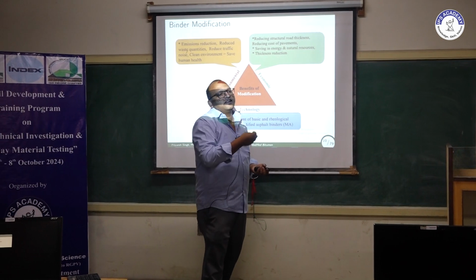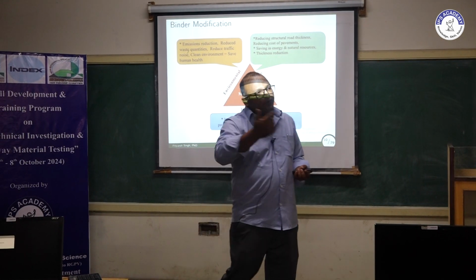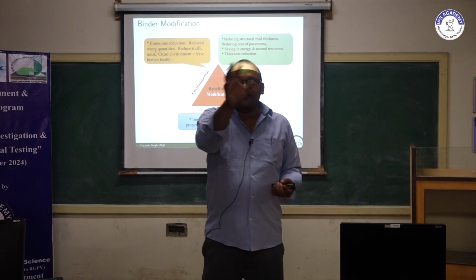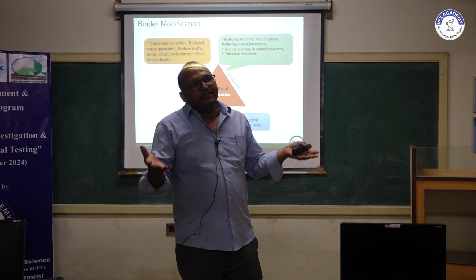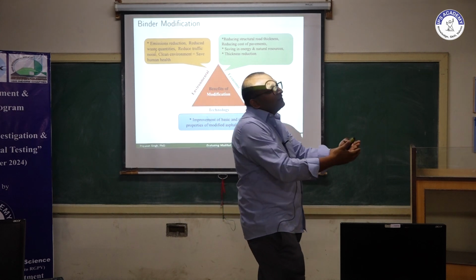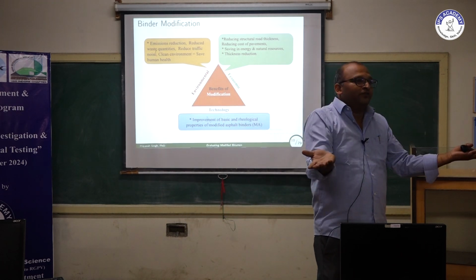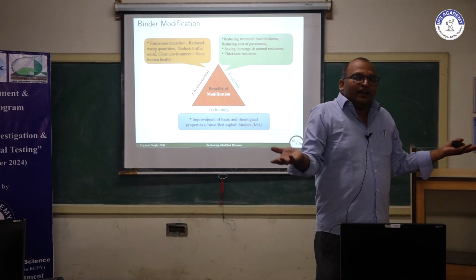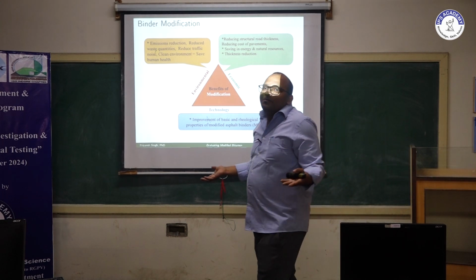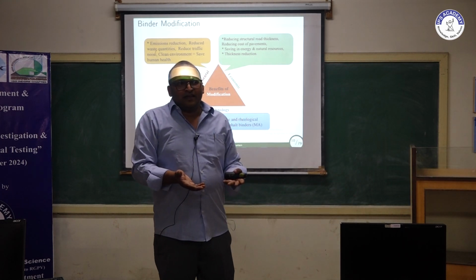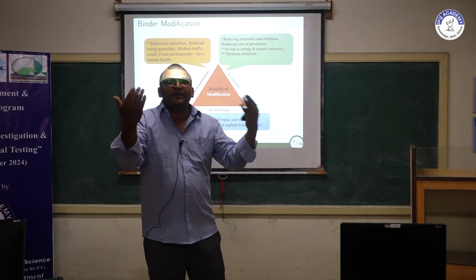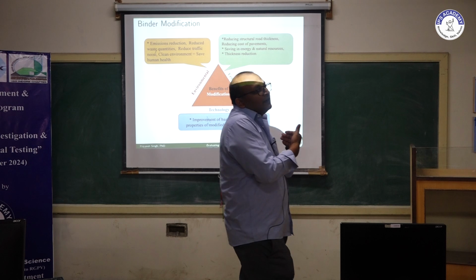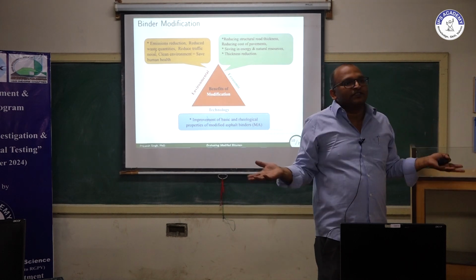But if you see, the softening point value for most neat binders comes in the same range I am talking about, around 50 or 55 degrees Celsius. That means at that temperature my binder is going to be soft enough to get deformed. So I need to make my binder stronger. I need to increase this strength so that it can take more stress, maybe thermal stress, or other climatic stress, or other kinds of stresses.